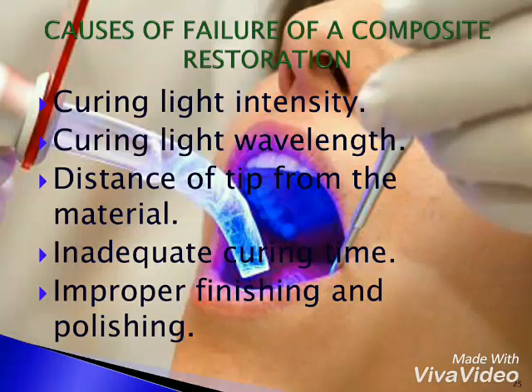The curing light intensity and wavelength are also very important. The distance of the curing tip from the composite restoration is also very important. Curing time is also critical — if there is inadequate curing time, the polymer in the dental composite won't get polymerized and the restoration will more likely get dislodged easily.